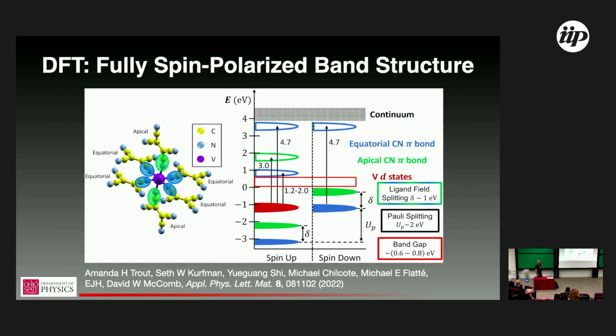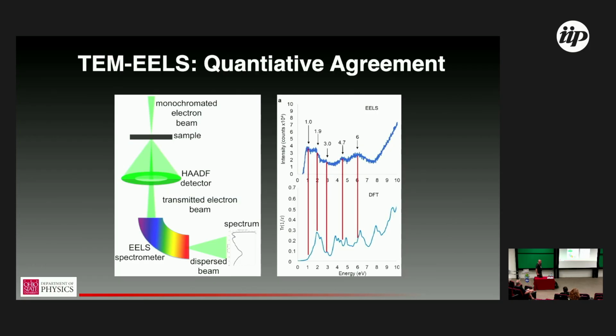Carlos, as ever being a thoughtful host, is a perfect segue to my next slide, where I show the integrated density of states from the DFT, as well as energy loss from the electron microscopy. And there's some dielectric modeling that one needs to do in various things. Oh, did I say the wrong thing with density of states? Yes, that is actually what it shows there, which is 1 over the dielectric function. Sorry, it does include the matrix elements.